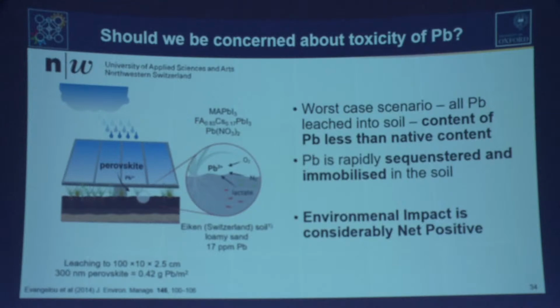That's not to say that the lead is toxic at all. In fact, it's very good. Compared to burning coal, it's orders of magnitude better. But the presence of lead has a very minor impact. And in fact, if it did leach into the soil, we found it gets sequestered by the soil very quickly, and we've done experiments to investigate that. So it won't then go forward into the water supply. So it's actually very safe to deploy.